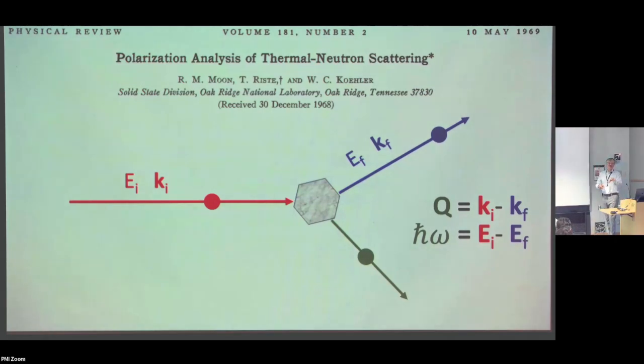Yeah, so let me just say a few words about polarized neutron diffraction, which is really a cool technique. So this is what we've been talking about so far, just having an incident wave vector, a scattered wave vector, transferring momentum to the sample, but we didn't really keep track of the neutron spin as much. We were always summing over incident spin state and scattered spin state. And you could say, why did we do that? That's because we wanted to maximize flux, so we didn't want to get into the trouble of trying to determine the spin state of the incident neutron, nor casting away the spin state of some of the scattered neutrons. So that's the high intensity experiment, and it works pretty well.